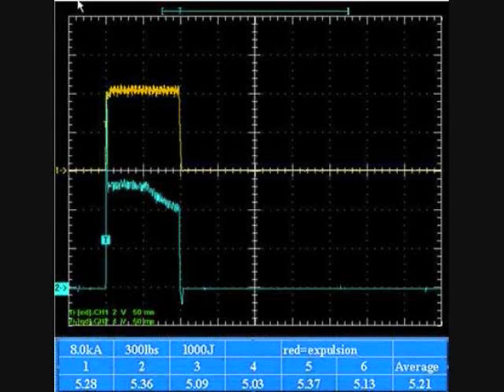This is the first picture. The yellow color trace is the current. I was welding about 8.0 kiloampere, 300 pounds of force, and 6.35 millimeter weld cap. I set the energy I want to put in to 1,000 joules. So this welded about 100 milliseconds. And the output average for 6 coupons is 5.21 millimeter diameter.